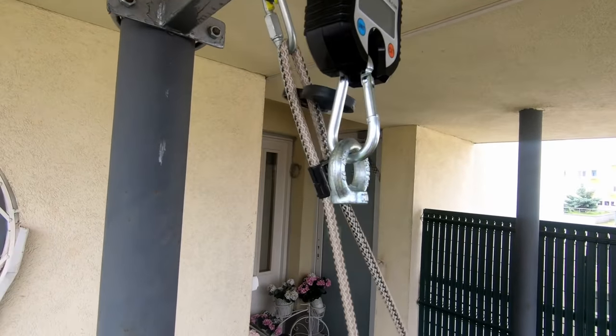Calculate twice and measure once. All results from the test are summarized in this Excel table, and it's obvious that a bolt printed in horizontal position is much stronger than one printed in vertical position, but let's not forget that in this case we need supports for this printing. It will be a hard decision which one to use in the future.